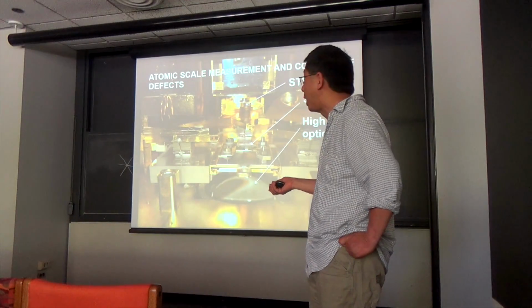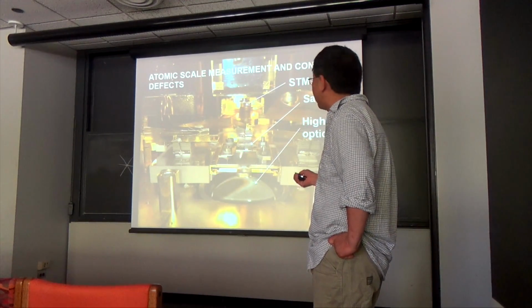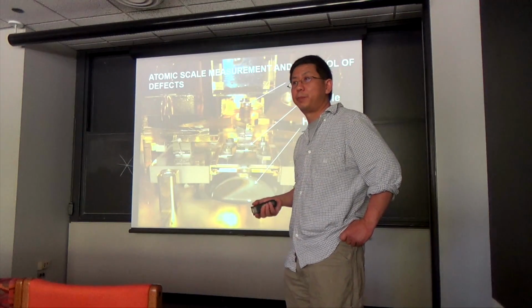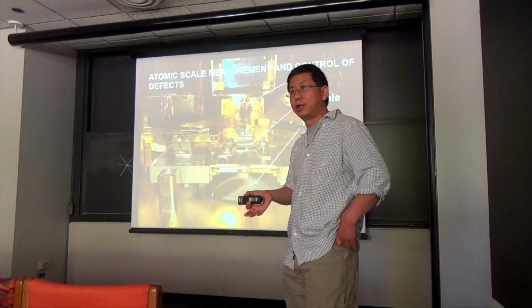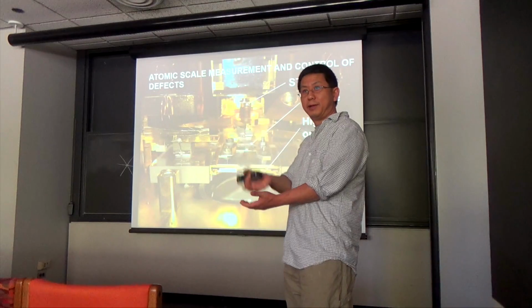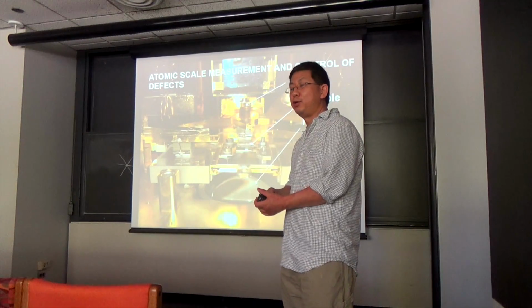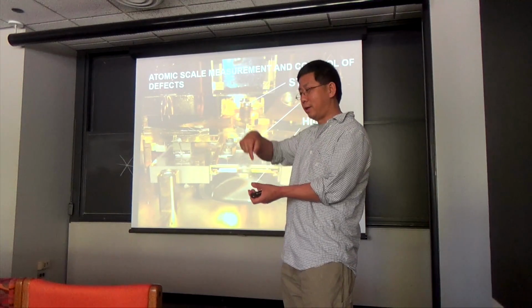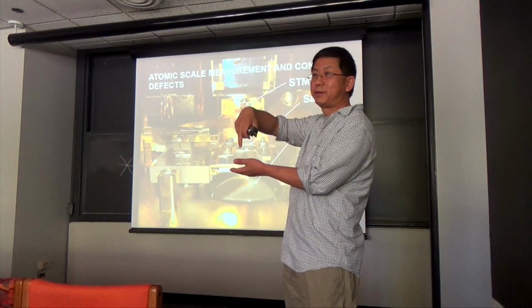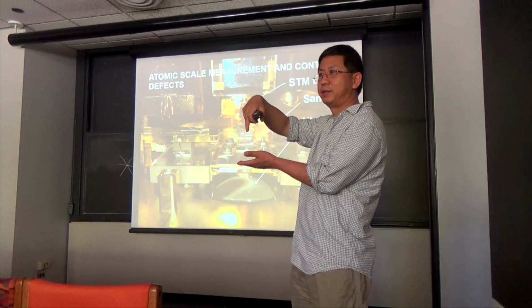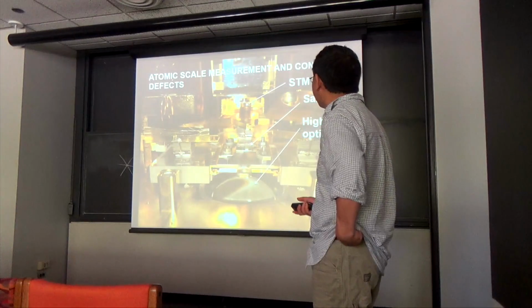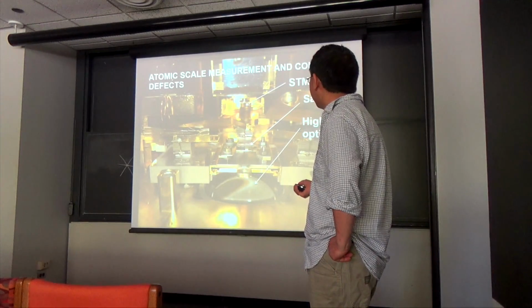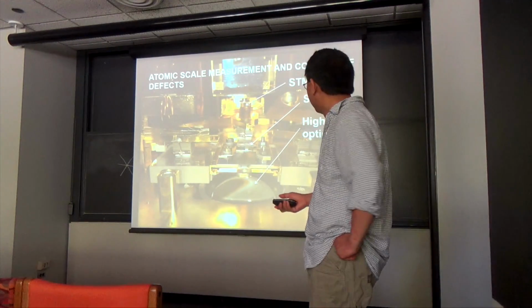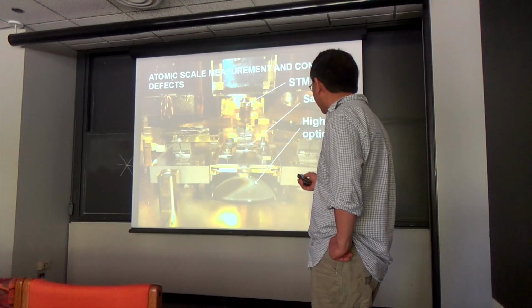Everything you cannot really buy commercially, and these are extremely difficult experiments, because a lot of the time when you shine a laser on the sample, it expands really quickly. One of the STM's working requirements is that you have to maintain the distance between your tip and sample, and you have to be able to account for the expansion of the sample. So these are very difficult experiments.